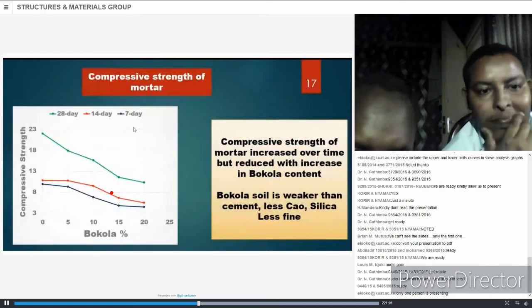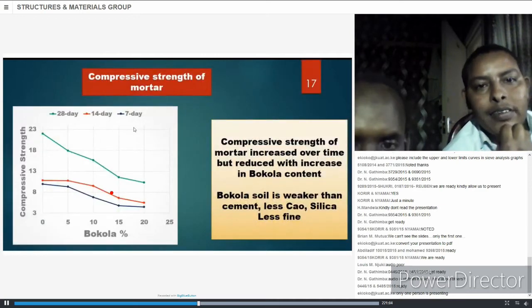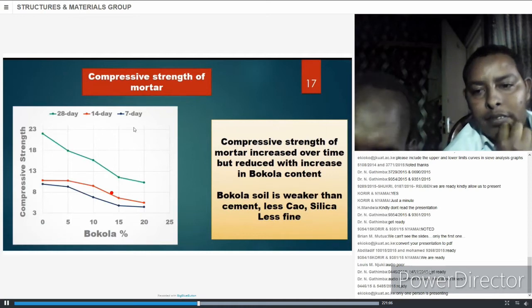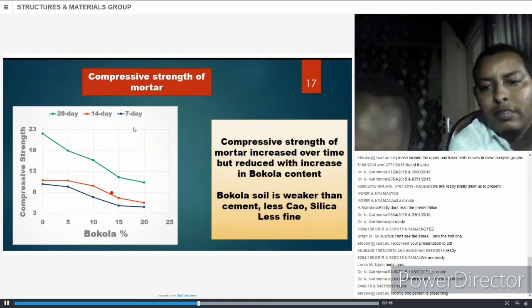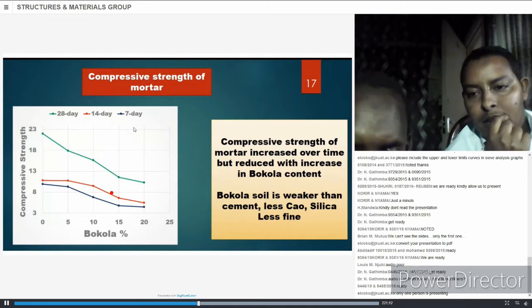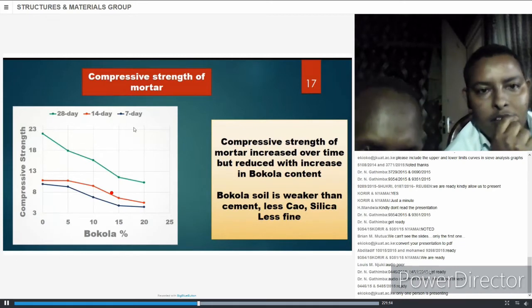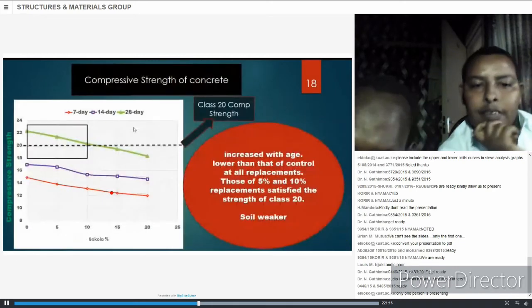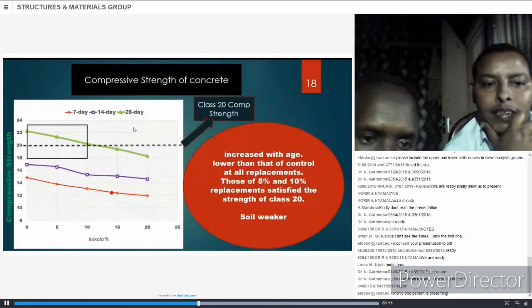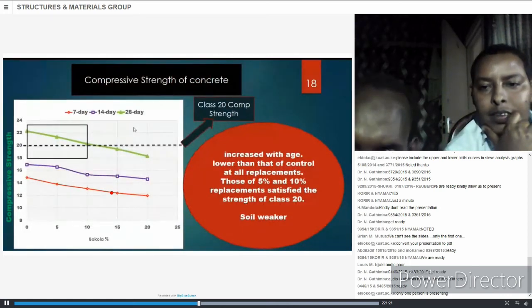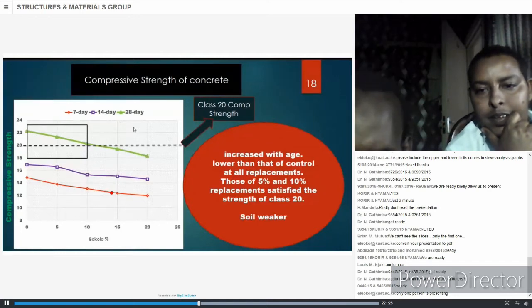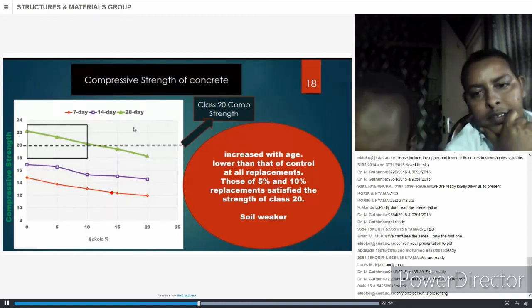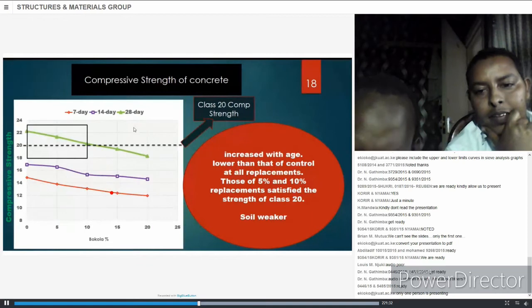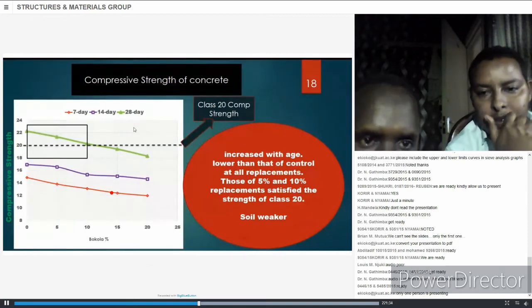Compressive strength. The compressive strength of mortar also increased with time, but reduced with increase in bokola content. Bokola is weaker than cement due to less calcium oxide, less silica, and it is also less fine. The compressive strength of concrete also reduced with increase in bokola content, but increased with age. It is lower than that of the control at all replacements. Those of 5 and 10% replacement satisfied the strength of class 20, and this shows the bokola soil is weaker.